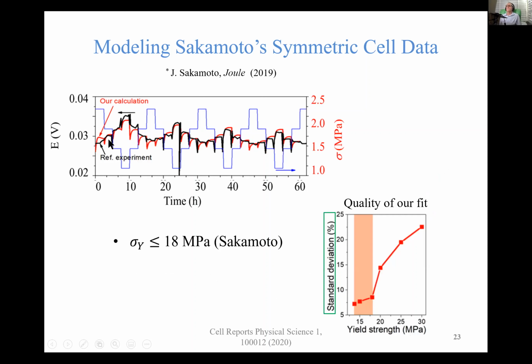So this graph shows our prediction, or our model, in red against his data in black. And we used, as I said, the yield strength as an adjustable parameter. Now, we wanted to look at the sensitivity of the yield strength in terms of how sensitive our fit was to its value. So we looked at the standard deviation between Sakamoto's data in black and our prediction in red, and we compared that standard deviation to values that we chose for the yield strength. And what we saw is, over a very narrow range of yield strength values that we chose, we got good fit. But as soon as you got above about 18 megapascals, the fit got terrible, and there was just nothing we could do to get a decent fit.